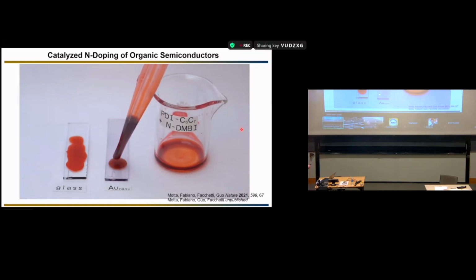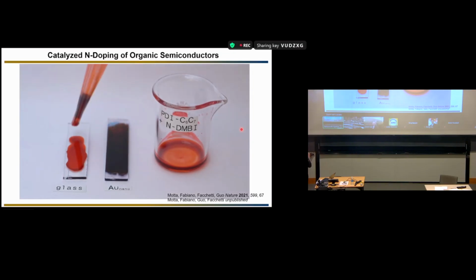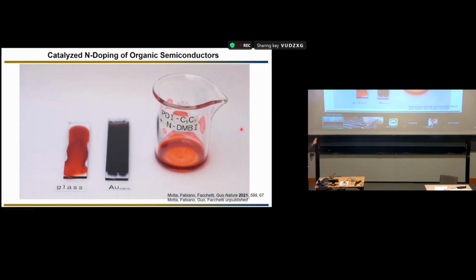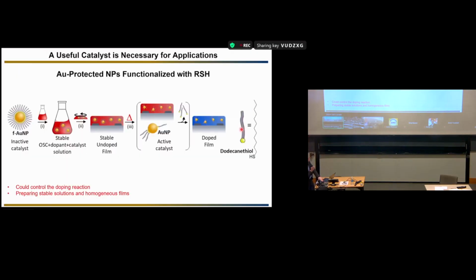If you do it with a little catalyst, you see they change the color. Change of color means the reaction happens. So the reaction happens instantaneously. Okay? So using catalysis is really a way to enhance this doping ability of organic molecules. This is bad, but also this is bad. This is too slow. This is something you cannot control because you cannot create formulations which are stable enough to do the chemistry. So this is the last thing I'm going to tell you.